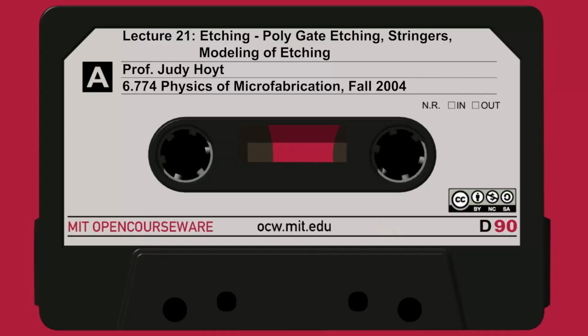And we also mentioned at the very beginning of the last lecture, gate dielectric damage due to the antenna effect. What is that? You have ions coming down, being collected by the gate. Where do they go? Well, they don't go through the field oxide because that's too thick. They get shuttled down the gate and the current tends to go through the gate oxide. You have to be careful that you don't put too much current through your gate oxide and damage it. So those are some basic issues when it comes to poly gate etching.